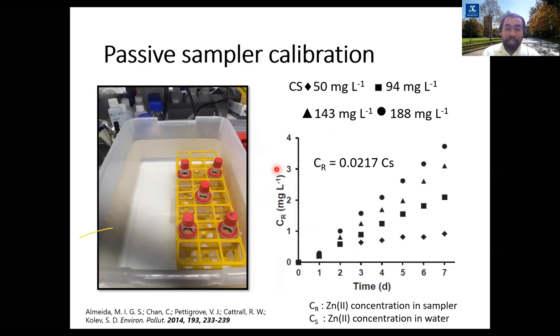So after the optimization, the passive sampling devices were then calibrated. We did the calibration in the lab. We basically have a model of our water system here outside. This is a model of our water body. We have some zinc in here, and we have the receiving solution inside our passive sampling devices. What we did is calibrate the passive sampling device using the source solution outside, containing different concentrations of zinc, as you can see here.